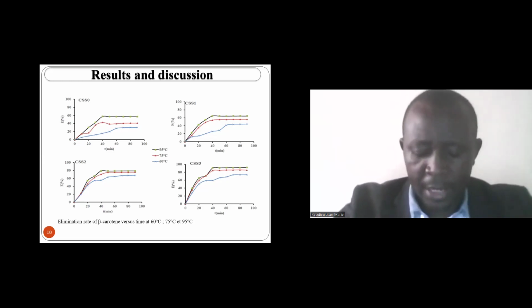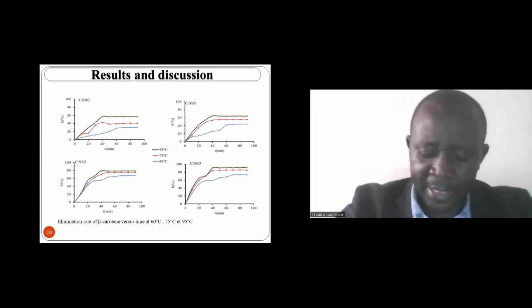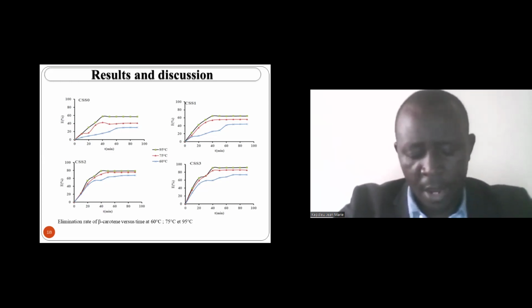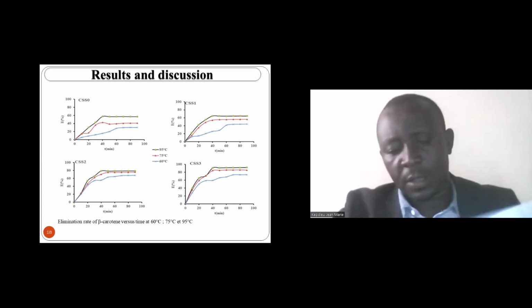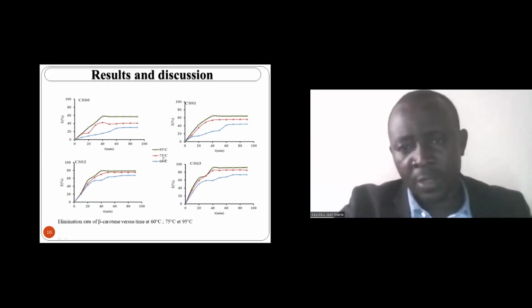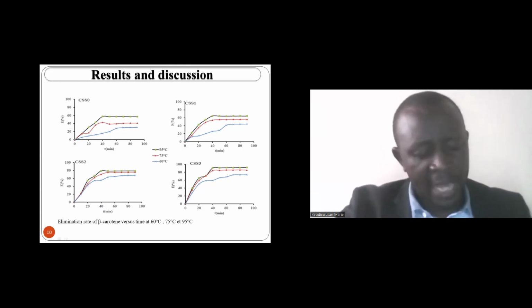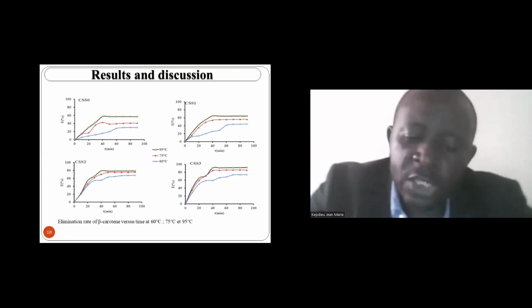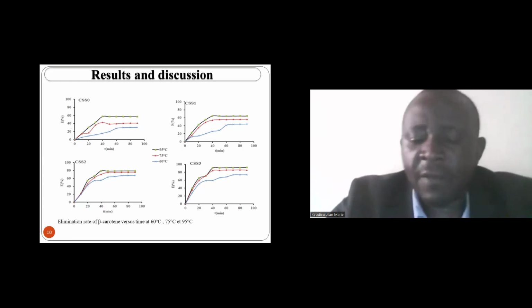So it follows the steady state. We also noticed a steady state indicating the equilibrium. And for the last two temperatures, 75 and 95 degrees Celsius, the equilibrium time obtained is within the range reported in many works, generally between 15 and 45 minutes. This means that adsorption equilibrium time decreases when the temperature increases.